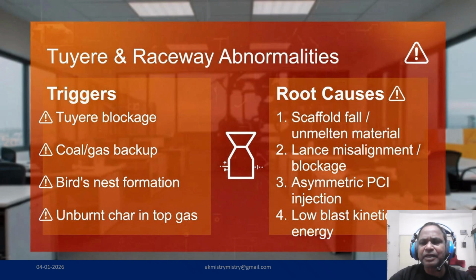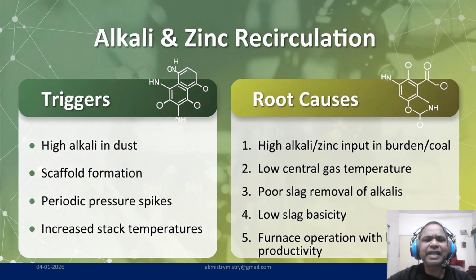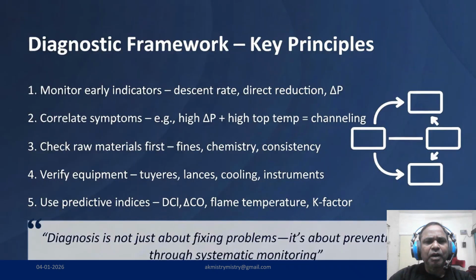Now, a silent killer in the furnace operation is alkali and zinc recirculation. You will identify this through high alkali in the dust, periodic pressure spikes and increased stack temperatures as scaffolds begin to form. These elements enter through the burden and coal and recirculate if there is a low slag basicity or poor slag removal. Operating with low productivity or low central gas temperature further encourages these elements to condense and build up on the walls.